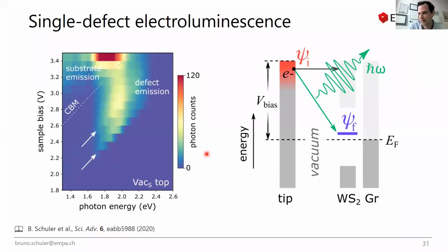In my opinion, it has to be a single photon emission, because we inject a single electron. There can be just one electron at a time, because if you inject the electron and populate this defect state, there is nothing else around that you can populate with electron tunneling. Also, by energy conservation, the energy difference between injection and final state exactly matches the photon energy that comes out. So in my opinion, it is trivial that this is a single electron conversion into a single photon process. We would love to do the G2, but we don't have enough time, not enough counts.